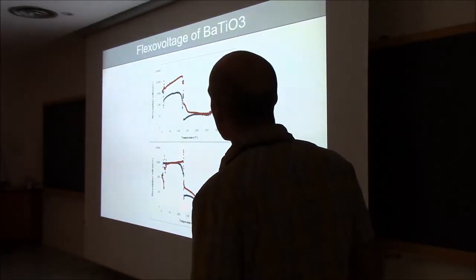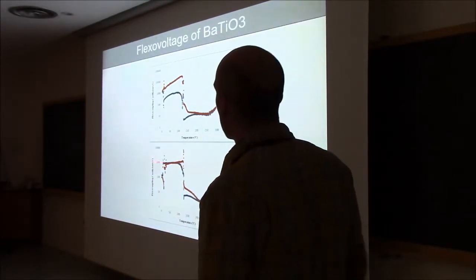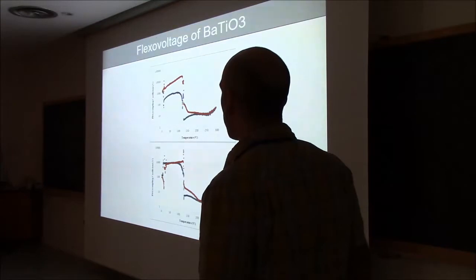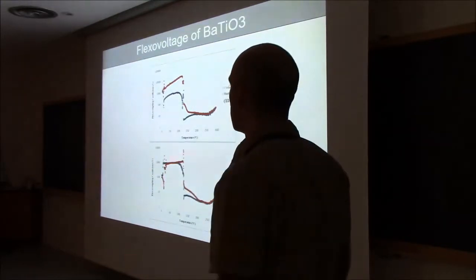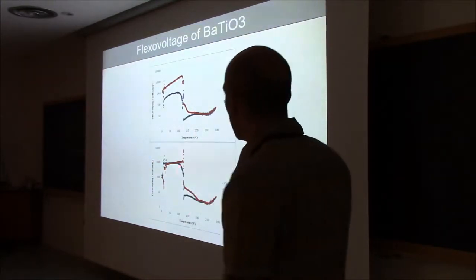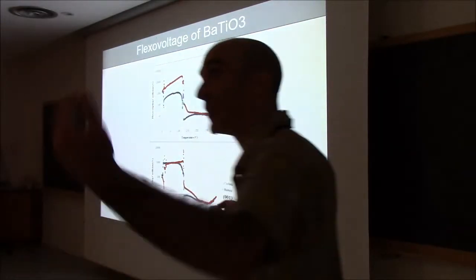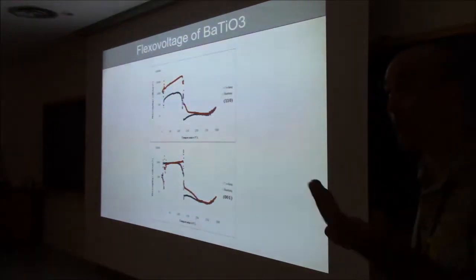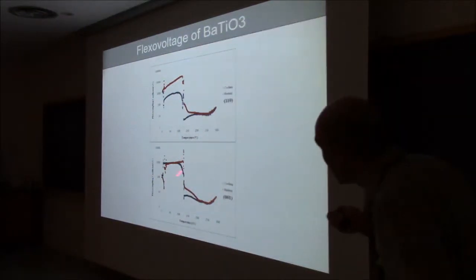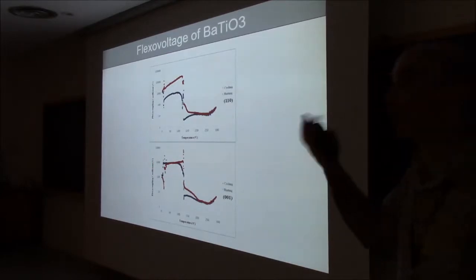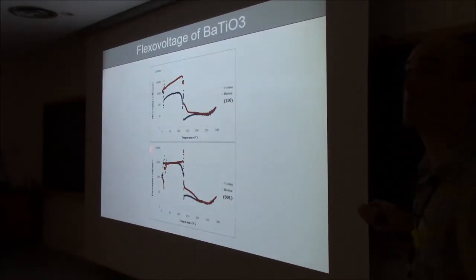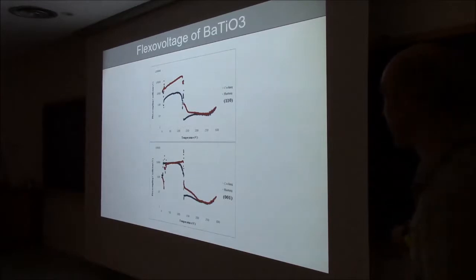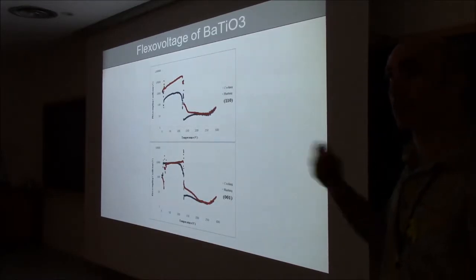And then at low temperature, the thing jumps, goes through the roof, and it becomes enormous. Here, we are certain that this is due to piezoelectricity. Okay. So here, we are already in the low temperature state of BTO, which is ferroelectric, and therefore also piezoelectric. So we think that this enormous flexocoupling coefficient is not real, it's piezoelectricity. You were asking about that earlier. This, however, looks very much like what it should be.